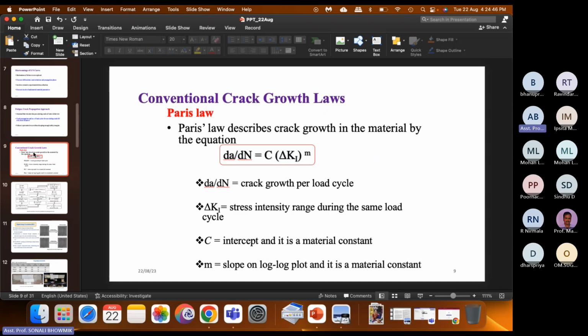This is the conventional crack growth law, which is called Paris's law, which is specifically developed for metallic structures. You can see here da/dN = C ΔK to the power n. da/dN is nothing but our crack growth rate, ΔK is the stress intensity factor, and C and n are two constants. So this is the conventional crack growth law, based on this one can find out the crack growth rate.